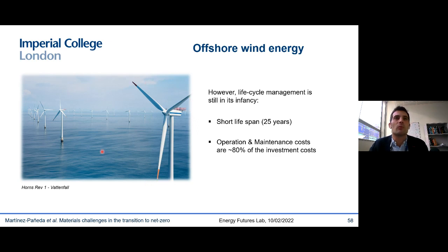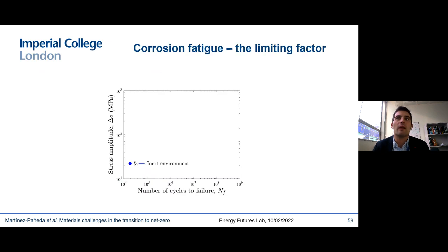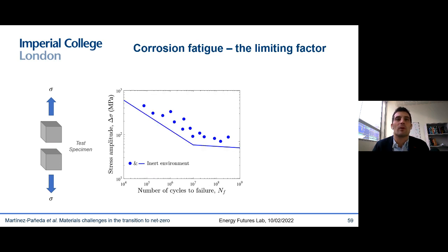And here, the key thing of what limits the lifespan is the corrosion fatigue of the support structure of these structural monopiles, which are made of structural steel. And let me explain the way in which the service life of these support structures is currently being determined in engineering practice. This is essentially done using what is called SN curves, stress number of cycles to failure curve. So this is the stress amplitude, and this is the number of cycles to failure. So what you do is you go to the lab, you take a smooth sample, and you test it under cyclic loading. You pull up and down, and then record the number of loading cycles that it took to fail. So you have 1 point here, and then you do this for multiple load amplitudes, and then at the end, you get all these data points, and you draw what is called an SN curve.